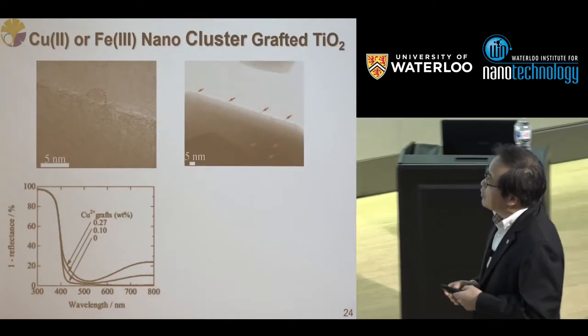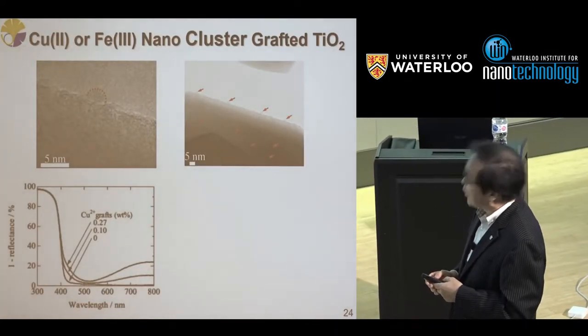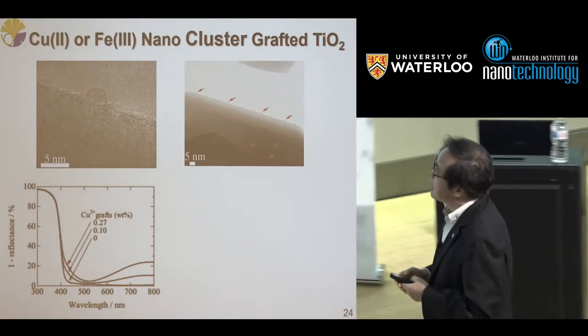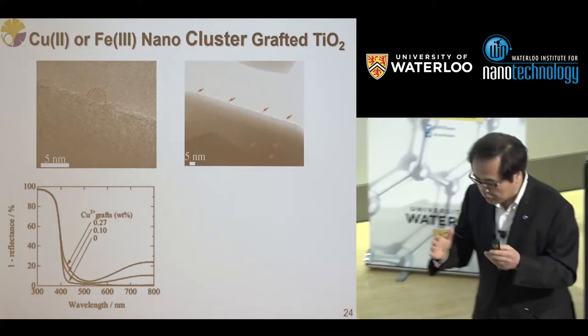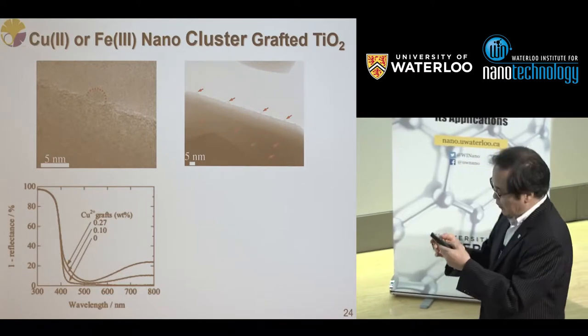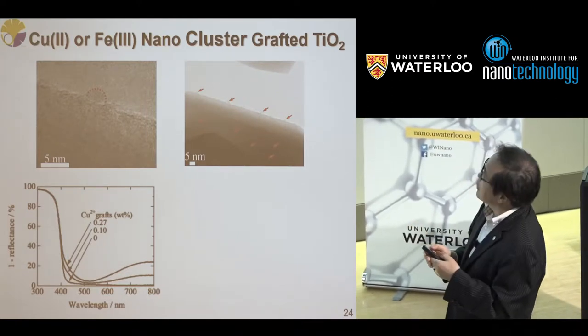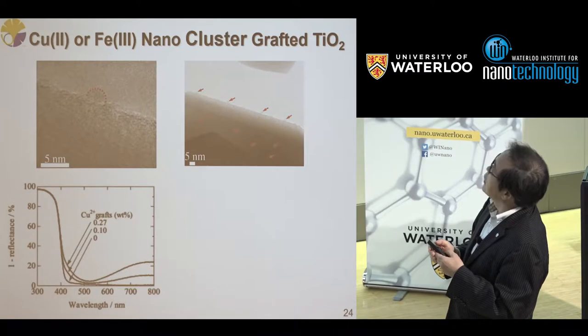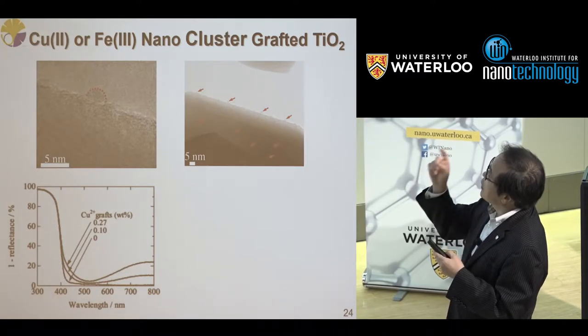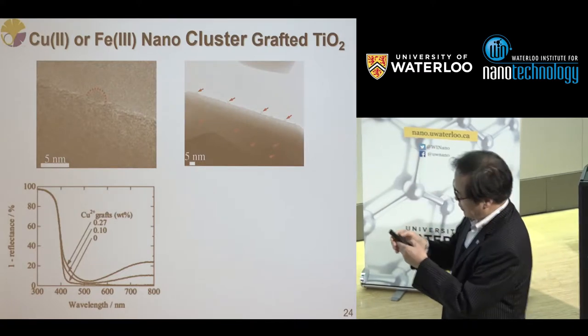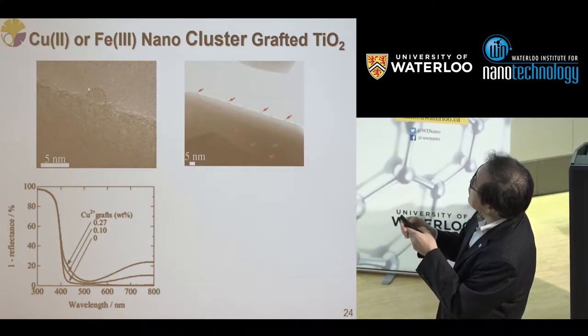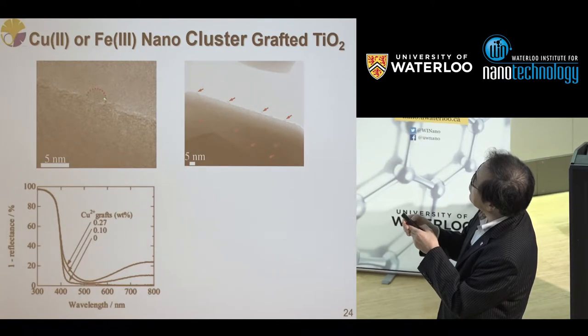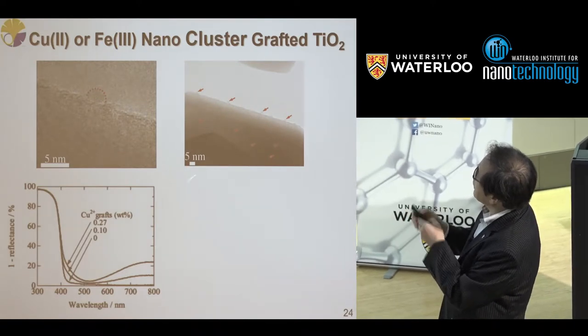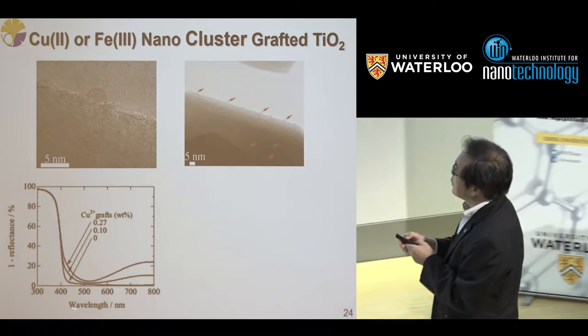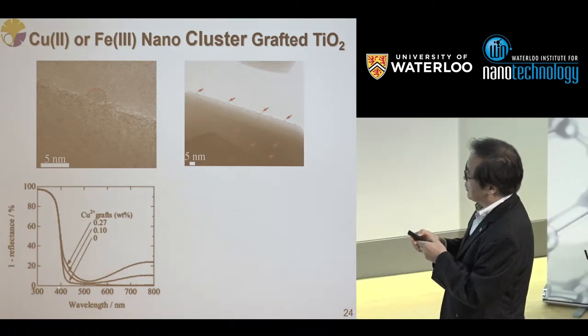About 10 years ago, more than 10 years ago, we found, I won't go into the details today, but when the titanium dioxide surface is grafted with divalent copper or trivalent iron nanocluster, like this, this is 5 nanometer, and this is a divalent copper case, so 2-3 nanometers, like this. Then we have the new absorption in visible light.